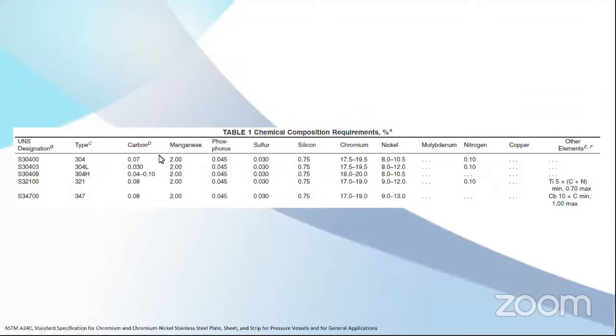This is just an example. So what is the difference of the stainless steel? For example, 304, you have maximum carbon 0.07, but if you use L grades, you have maximum 0.03. And this is the stainless steel with stabilization elements. 321, you have titanium. 347, you have niobium. You can have higher carbon, 0.08, but the carbon is taken by the titanium or by the niobium. So you have no problem with the chromium carbides. It's already reacted. All the carbon is already reacted with titanium or the niobium. So there is not enough carbon to react with the chromium.